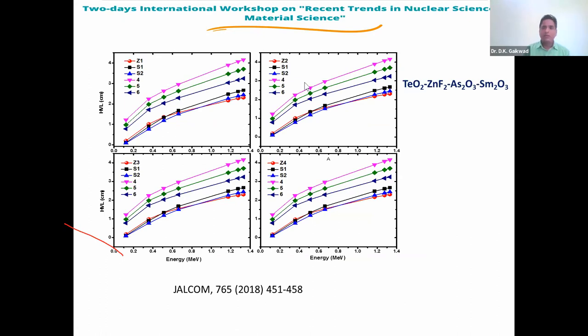Then another study: we synthesized tellurium based glasses and compared our glasses with S1, S2, which are glasses, and 4, 5, 6, which are concretes. These are the steel concrete, and the ordinary and heavyweight concrete. And these Z1, Z2, Z3, Z4, Z5 are tellurium glasses. If you see Z1 here, in the very first diagram, the half value layer of the synthesized glasses is very low compared to the concretes.